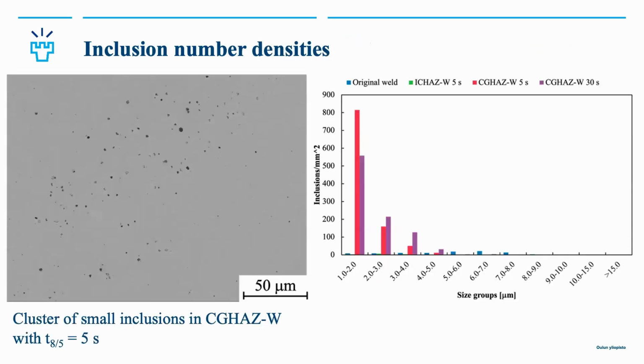Okay, then I'd like to tell something about the inclusion results. They are quite interesting. They are still preliminary results, and we need to do some further scans to confirm, but I am showing this because they look quite interesting. Because here, oh, the laser stopped working. Anyway, you see here the coarse-grained heat affected zone, and in these cases we have a lot more small inclusions than in the original weld and in the intercritical heat affected zone.